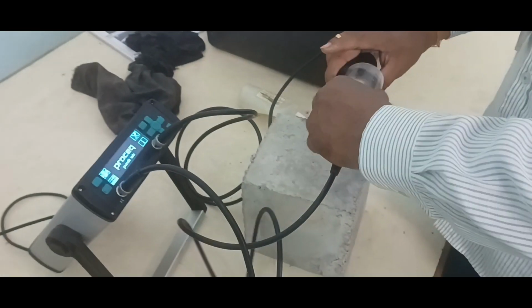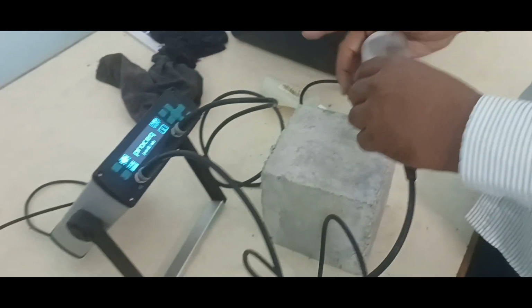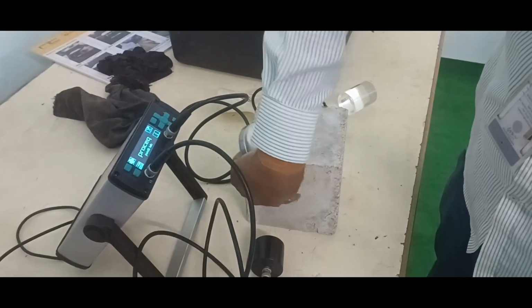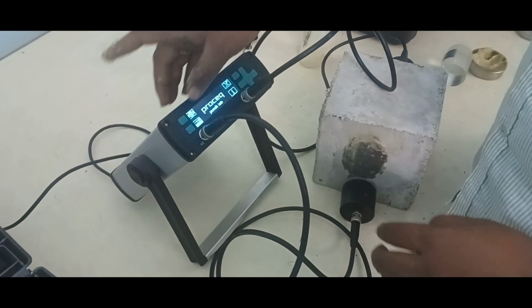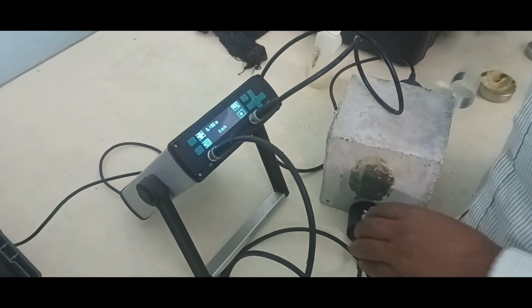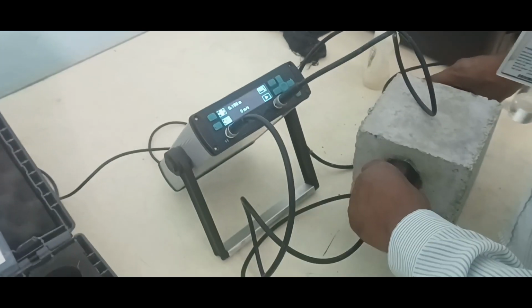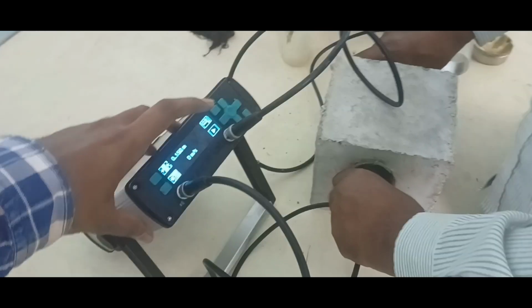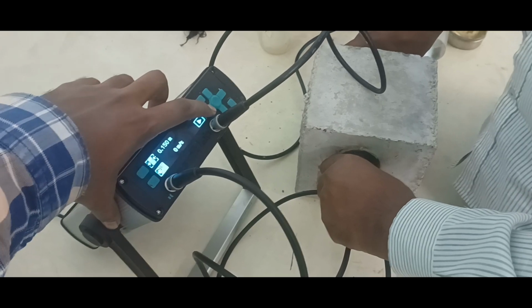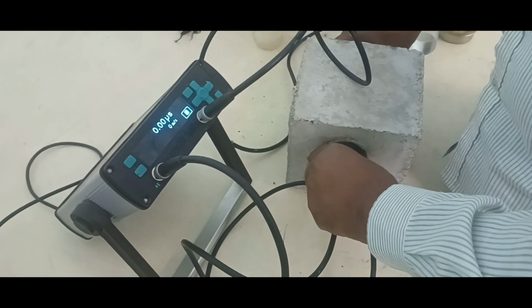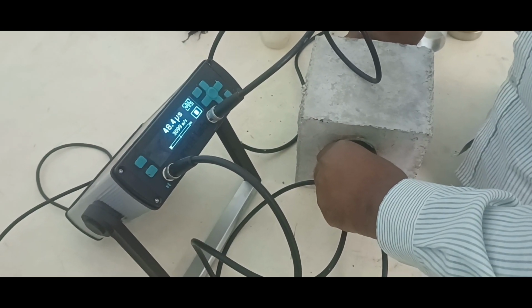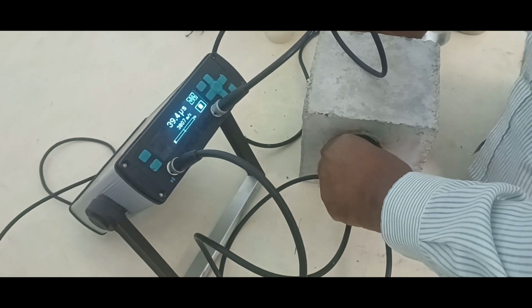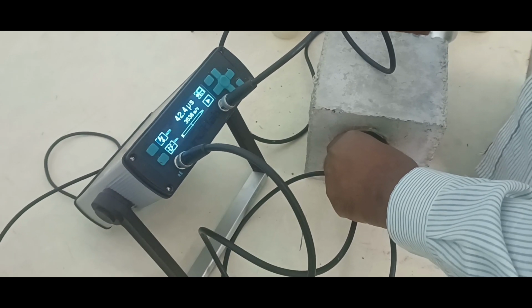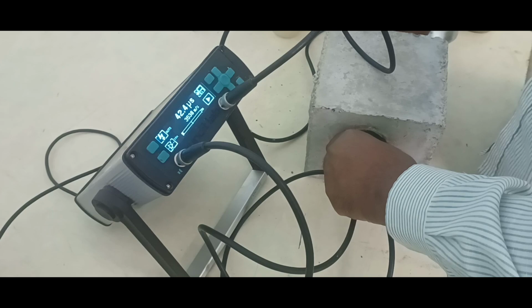So we have one concrete cube with us, and that cube we are going to test. For that, you need to apply grease on the faces where you are going to attach the transducers. A very important parameter here is the length. You have to give the length as it is, which you can see directly is 0.150 meter, so no need to change. You can press the play button. Now it will calculate the time and velocity. So 42.4 is the time, and below that the value is the velocity.